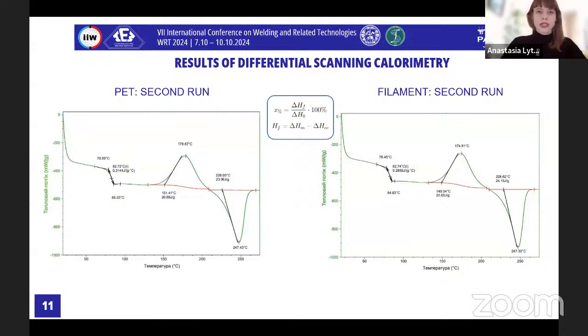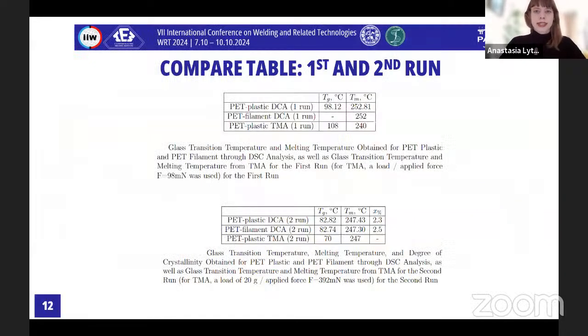Using the equation for defining the degree of crystallinity, it was obtained that the crystallinity degree for PET plastic is approximately the same as for the PET filament that we obtained on the second run. The melting temperature obtained from the DSC analysis for PET filament during the first run was 252. Other parameters from the first run graph could not be determined, as I mentioned before, so it's not very informative.